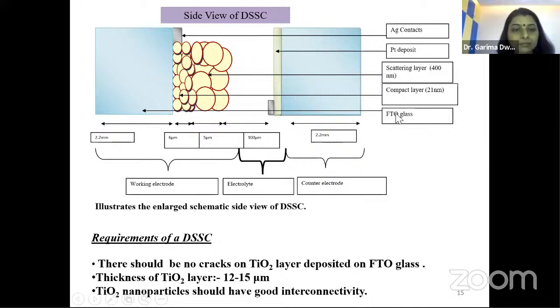Now we can see the dimensions of this. The size of this TiO2 nanoparticle layer is like 6 to 8 micrometers, and this is like 5 to 10 micrometers. It depends on what technique we use, whether we have some automatic machine for that, or we are using handmade techniques. So more or less the dimension is like this only. And this area is filled with electrolyte. So this complete part is known as the working electrode. This is the counter electrode, and in between is the electrolyte.